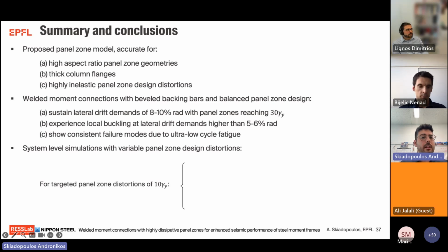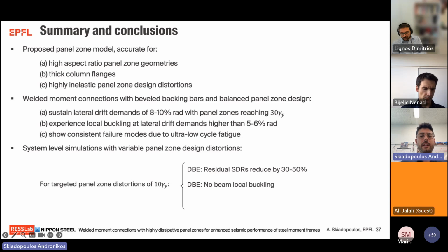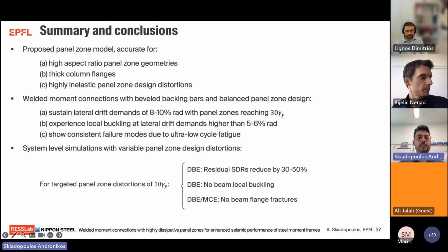Finally, the system level simulations showed that once we target the panel zone design to attain 10 times gamma y, the residual story drift ratios reduced by 30 to 50%, and beam local buckling is practically not evident, and the same applies for beam flange fractures.